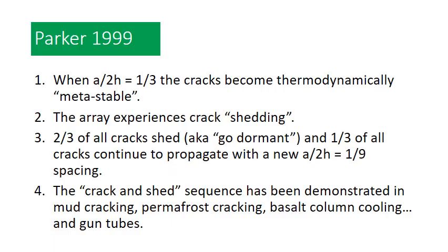Now, in 1999, in Parker's paper, he came up with a very interesting philosophy on how cracks behave. He basically stated that when the crack depth divided by the spacing ratio is equal to 1/3, the cracks become thermodynamically metastable. And we see that in the plateau of the curve. The A/2H ratio of 1/3 exactly corresponds to that spacing ratio we saw earlier of 0.4.